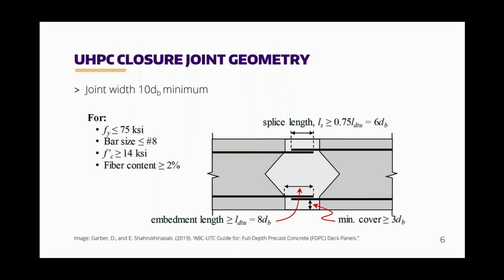The reason for it is, of course, its high tension and bond strength. It allows you to have very small closure joints as opposed to traditional cementitious concrete. And so you can see a typical geometry for that joint here. You have a minimum cover of about 3 bar diameters. You have an embedment length of 8 bar diameters, a splice length of 6 bar diameters. If you put all those things together for a bar with yield stress of less than 75 KSI, you get about 10 bar diameters in terms of that minimum joint distance. This is for UHPC with greater than 14 KSI compressive strength and fiber content larger than 2%. And for many applications, UHPC would be the logical choice.